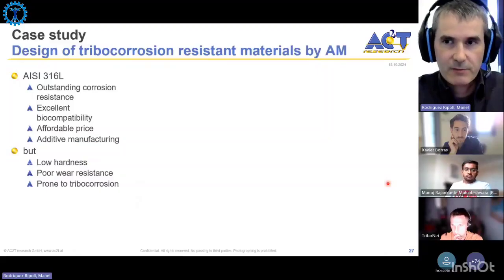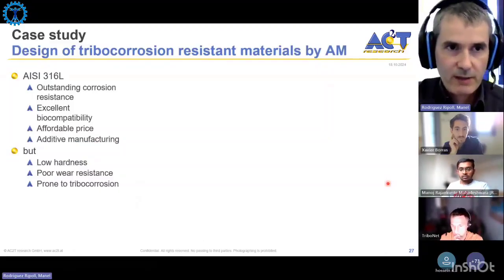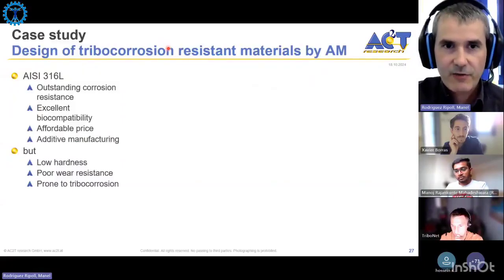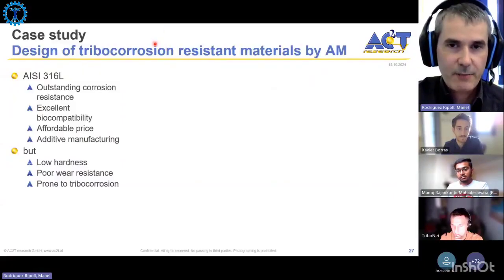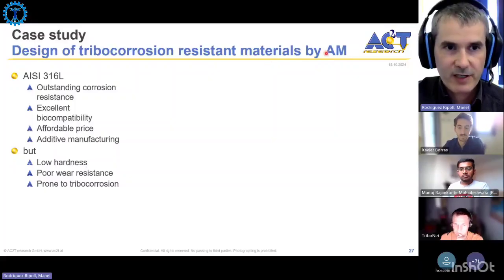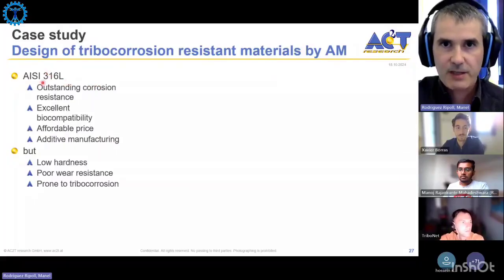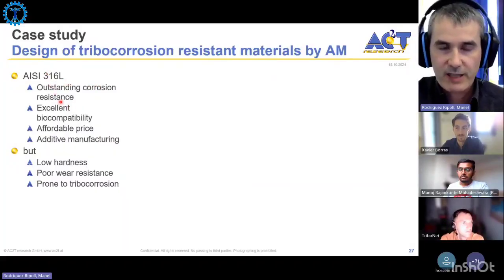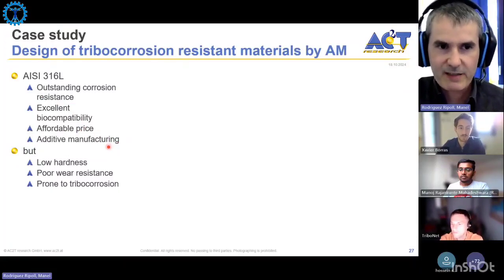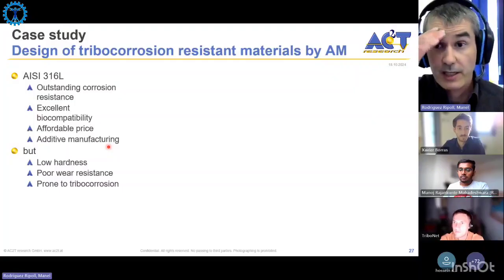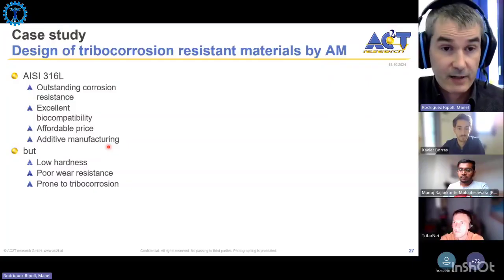Another case study that I would like to share with you is the design of materials that are resistant for tribocorrosion applications deposited by laser metal, so for additive manufacturing. The reason behind was that we were working with a 316L stainless steel, which is a material similar to titanium 6.4 with outstanding corrosion resistance, good biocompatibility. It's very affordable compared to titanium, and it can be also deposited by additive manufacturing, but it has very poor wear and tribocorrosion resistance. And the idea was, is it possible to improve the tribocorrosion resistance of this 316L?